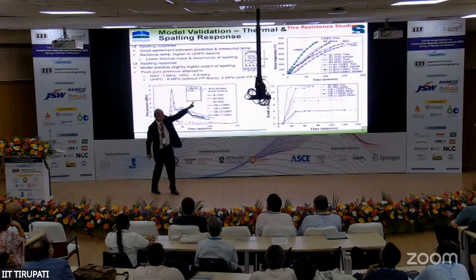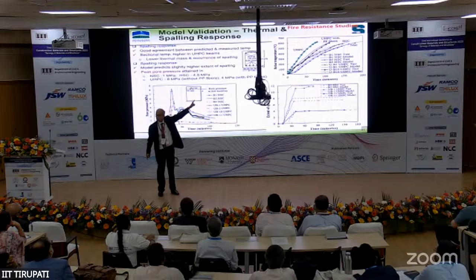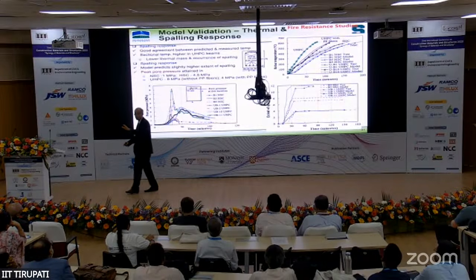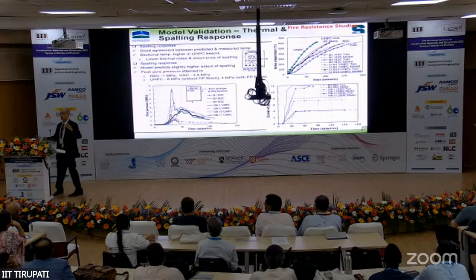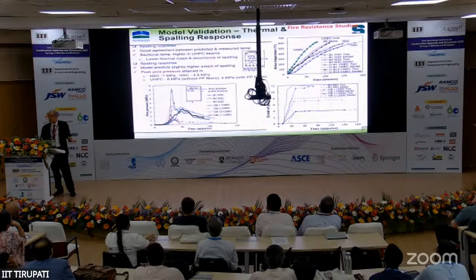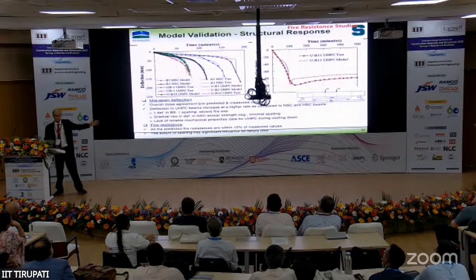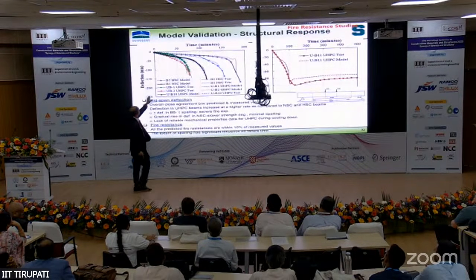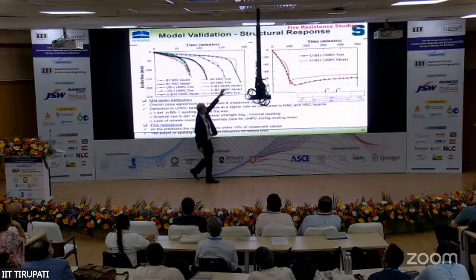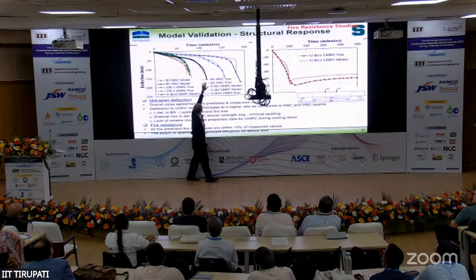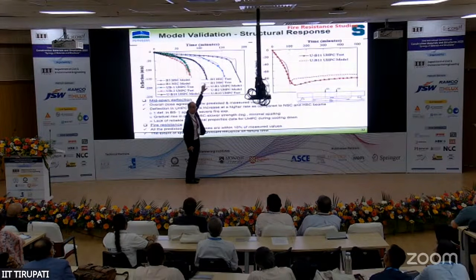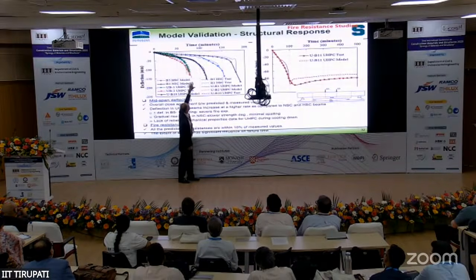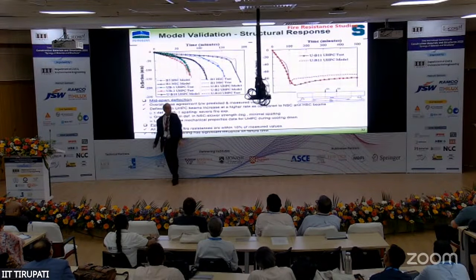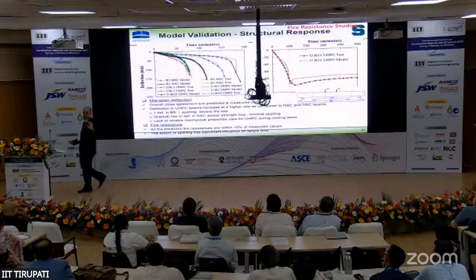UHPC, you can see the faster rise in temperatures. Normal strength concrete beam, slower rise in temperature. It helps the rebars to contribute to the tension stress. So normal strength concrete beam on the left-hand side, it's the deflection. Here normal strength, high strength, UHPC with only steel fibers. But if you add, it's the opposite. UHPC with steel fibers, if you add polypropylene fibers, you can increase the fire resistance.